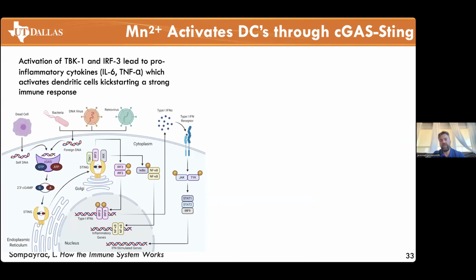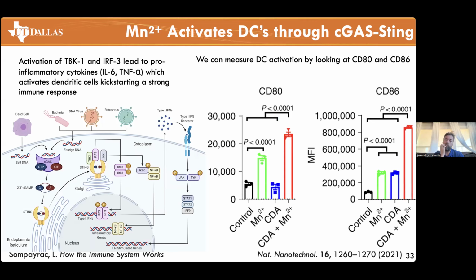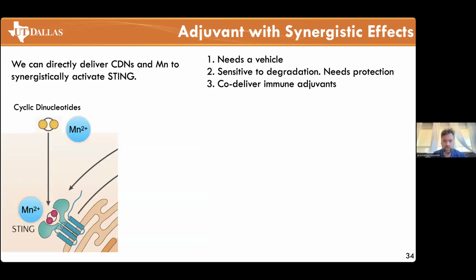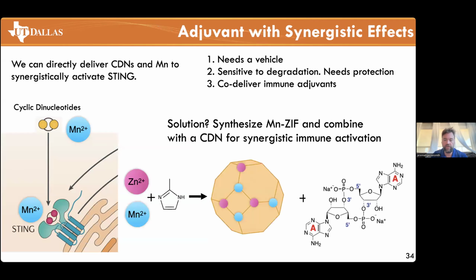And there is a pathway inside of cells called cGAS-STING, and this is an inflammatory response that is activated by extranuclear DNA. So when DNA gets into the cytosol, it shouldn't be there. The cell responds by creating an immune response, and essentially it becomes activated. And what people have seen is that manganese will turn this intracellular immune system on. If you add manganese to a cell, what you will end up with is expression on dendritic cells that show activation. Okay, so activation can be done very specifically using manganese. So we decided, what if we developed a metal organic framework that uses manganese as a specific way to activate this STING type pathway?